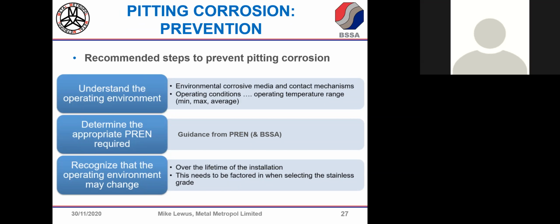Ways to prevent pitting. Well, obviously chloride. I particularly mentioned chloride, and I mentioned the maximum level we'd expect 316 to perform well at, and that's 1,000 ppm. 304, it's only between about 100 ppm to 300 ppm chloride, which is one of the reasons why it's not usually a starting grade I consider when people are asking me about materials to use in a marine atmosphere. So first, understand the operating conditions and look to choose a grade that you're comfortable will survive it.